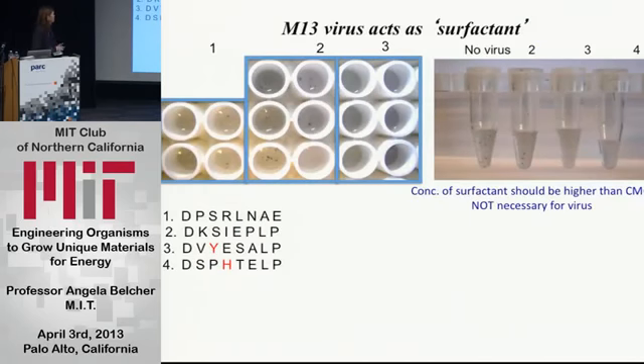And they selected viruses, and these are little dialysis chambers here. And so if it's in solution and you don't have a virus, you have clumping of these carbon nanotubes. And what they did was very, very clever. I don't think I have a picture of this. They made carbon nanotube mats, single wall carbon nanotube mats. They took their libraries and interacted them with the mats, and they pulled out the ones that bound the best.